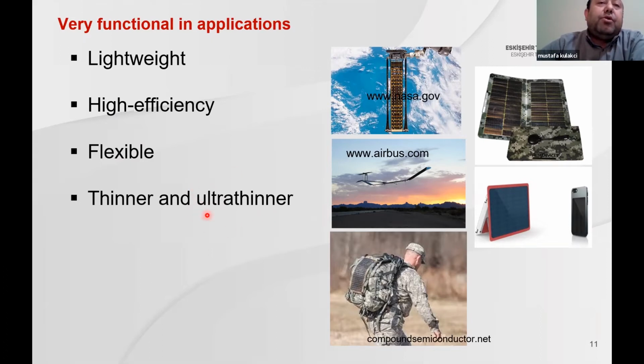The devices with only 2 micrometer thickness have been proven by researchers with an efficiency close to 20%. Of course, you can go up to 100 nanometers, but maybe you need some special texturing on the front side of your devices. When you look here, this is the NASA ROSA project. There is a rollable solar cell. Then in space, it is opened from the roll, and now NASA is going to increase the design or change it in a different way by using these devices.